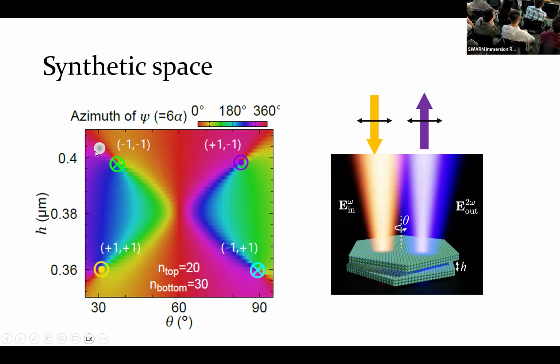And what happens is that, okay, if I start with this point and the system generates linearly polarized light, then if I move my system around it, just by changing H and theta, and go around that singularity, the polarization of the outgoing light rotates by 180 degrees. Okay. And now if I look at another point down there, then the polarization will rotate in the other direction by 180 degrees. Now there are some deep physics rules for these singularities I won't go into. But what happens if I put my system exactly on this spot? It would now generate circularly polarized light. This is kind of funny because we're putting in linearly polarized light, but what it generates is circularly polarized light. And this is again because the system has intrinsic handedness, so it's intrinsically breaking the left and right-handed symmetry. So we can generate this circularly polarized light just out of nothing.